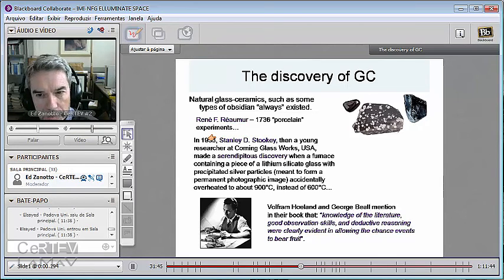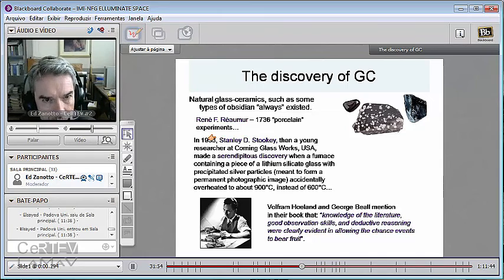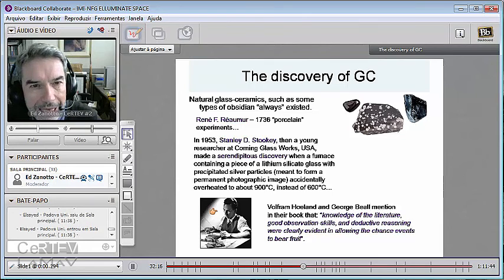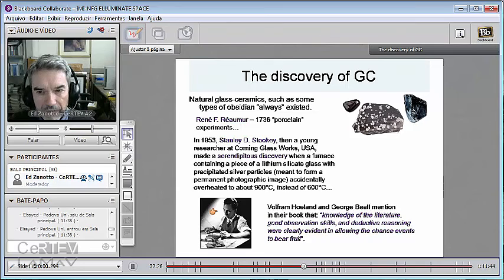important person, Stanley Stookey, who unfortunately passed away on November 4 last year, was 99 years old. In 1953, he was a young researcher at Corning. That's one of his pictures here, Corning Glass at the time. And he was working with a lithium silicate glass which had metallic silver particles, nanoparticles of silver. He was working with photochromic glasses, this kind of glasses. And he accidentally, one of his furnaces went up to 900 degrees Celsius instead of 550, 600 that he wanted, just to anneal the glass.